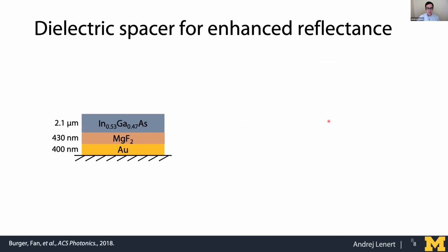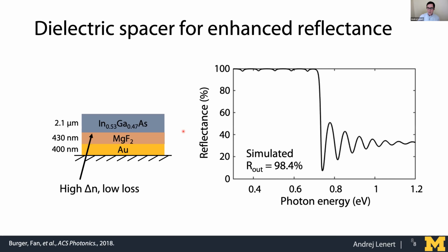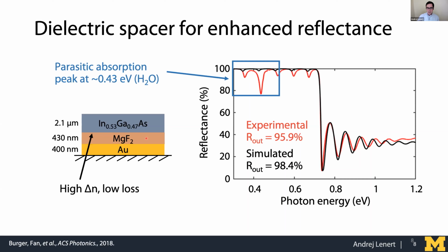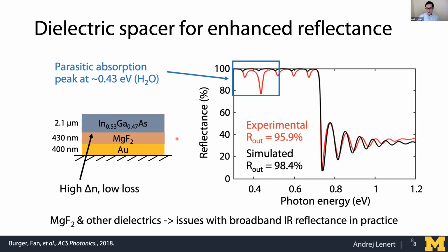Our initial work in 2018 tried to do this by developing an architecture where an InGaAs absorber was put on top of a low-index spacer and then on a mirror. And we were trying to improve reflection in this structure out of band. And theory suggests that the out of band reflectance should be close to 98 or 99%. But in practice, we saw parasitic absorption in this magnesium fluoride spacer. And this is something that we've noticed and other groups have seen as well, as there are issues once you start to actually deploy a dielectric spacer, a low index dielectric spacer behind the absorber.